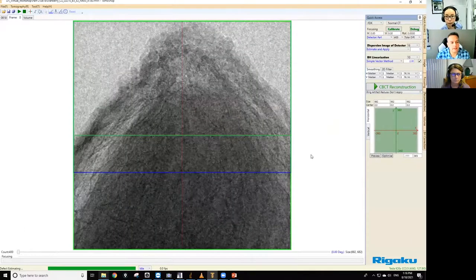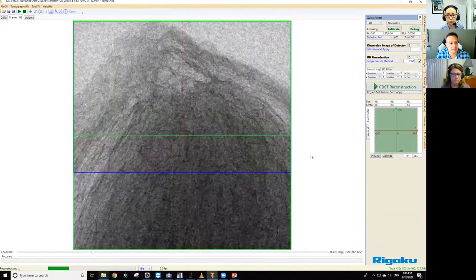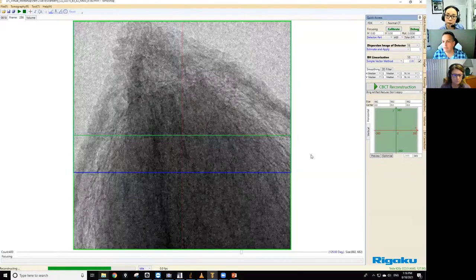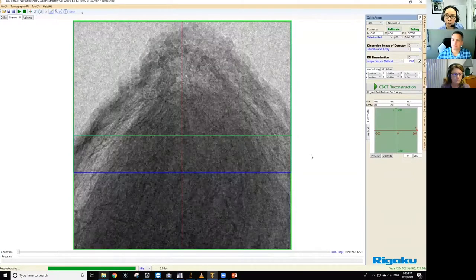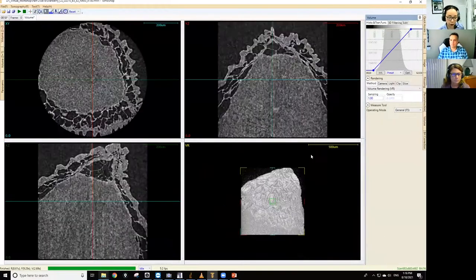So Aya, Mao has asked, can you just review the settings for that scan again? That was a copper source. It's a copper source. That means you have mostly 8 keV X-ray energy. And we have a 20x lens, and we're using binning 3x3. So that means your voxel size is 0.965. That's your voxel resolution. And we collected 400 projections in 2 minutes.